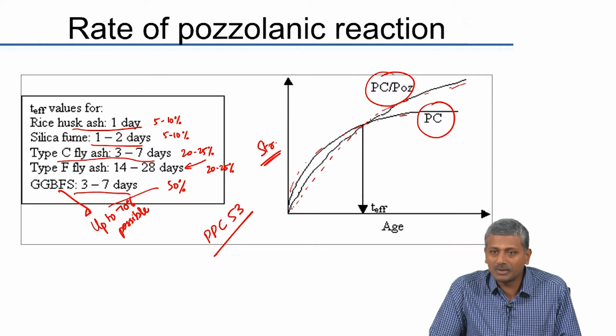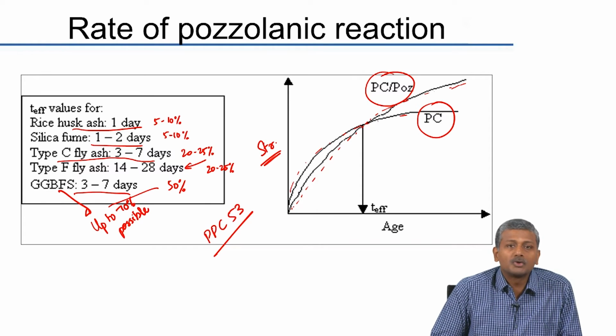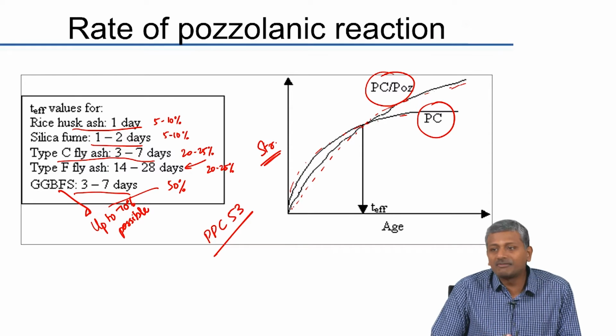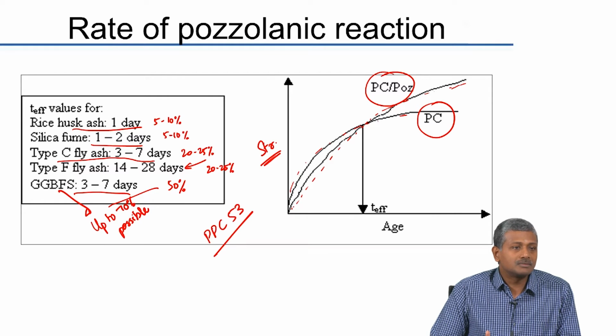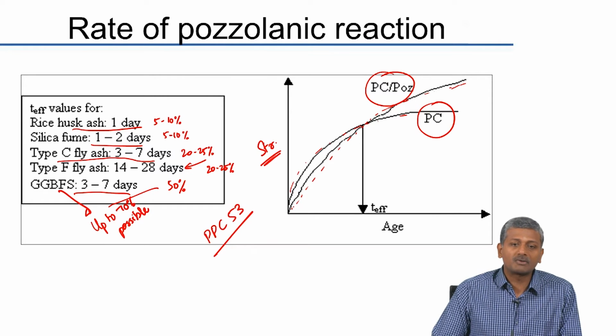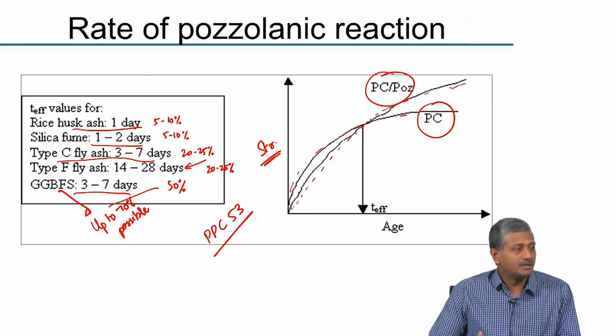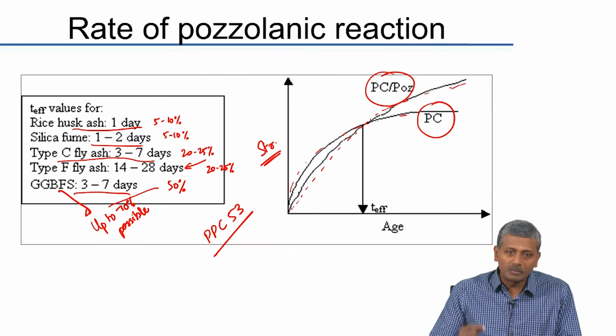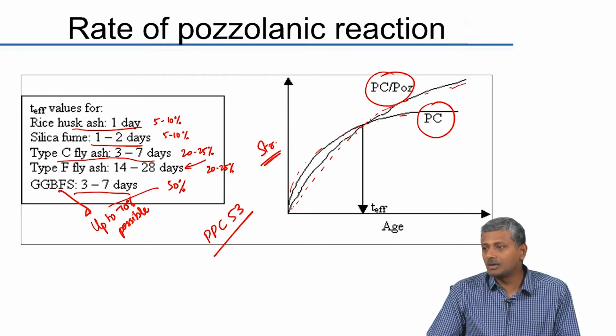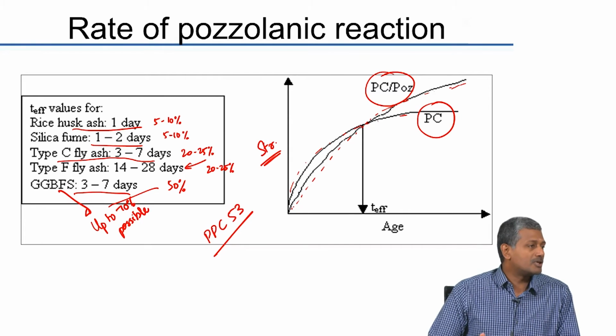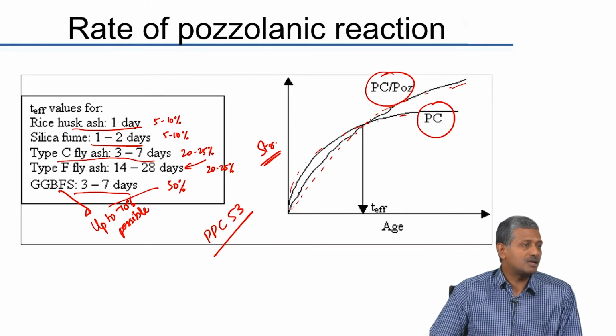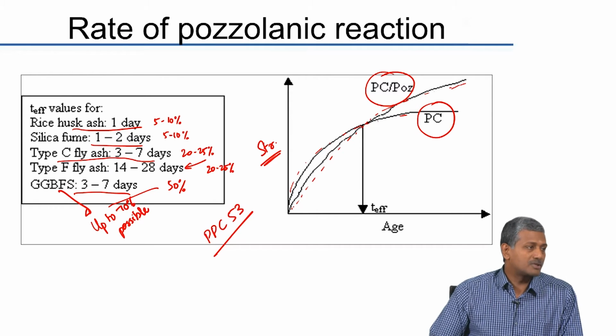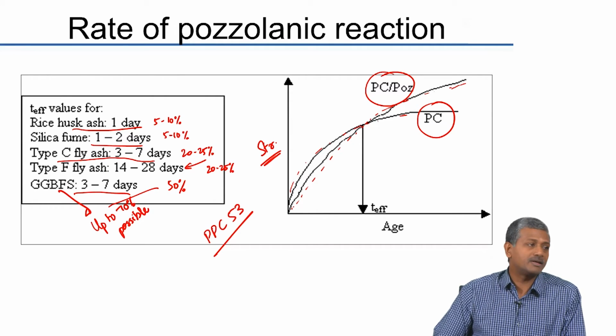Can we combine these together? So, very often when you produce very high grades of concrete like high strength concrete or high performance concrete, you can get significant benefits in combining more than one type of mineral admixture. For example, if you are preparing high strength concrete, you obviously will be using one of the finely divided mineral additives like silica fume. But we know very well that when you have too much fines in your system, your water demand will go up, your workability may be affected and so on. Because of that, the ternary combination or triple blend combination of cement, silica fume and fly ash or cement, silica fume and slag is often utilized to produce high grades of concrete.